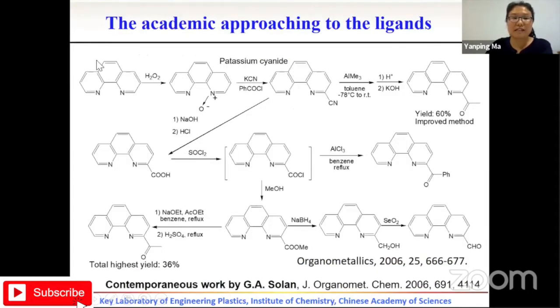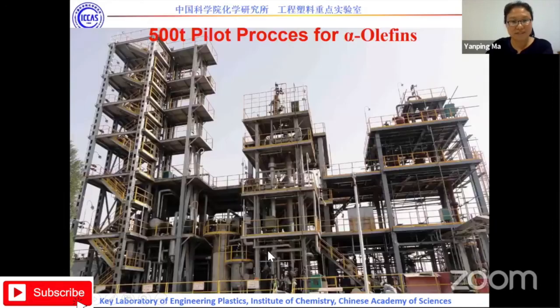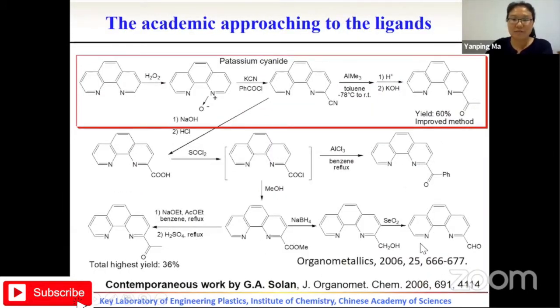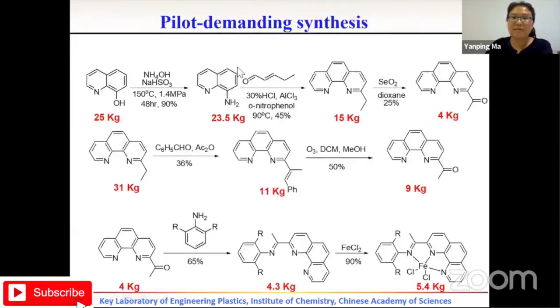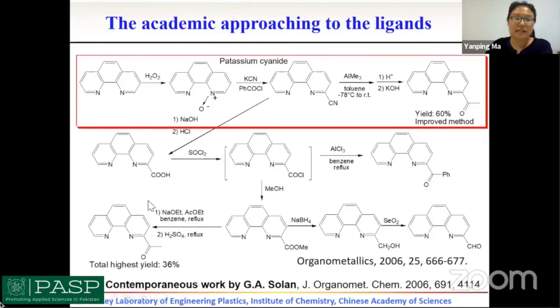Actually, this kind of ligand is hard to synthesize. It's not easy. We conducted this work, and Professor Solan from the UK also conducted this work. But fortunately, we have the past publications here to consider as sources for the synthesis. The potassium cyanide used here is not available in the lab at this time. It is very toxic. But at that time, we used kilograms of potassium cyanide to get just several grams of product. So we developed a new synthesis route.